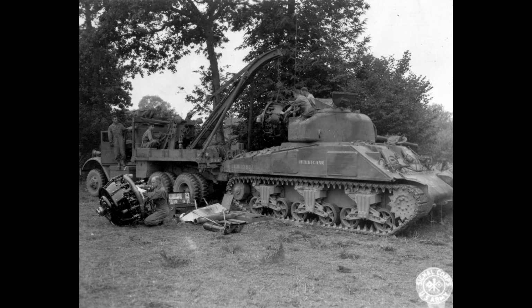The technical challenges were genuine. Welding armor plate wasn't like welding ship hulls or structural steel. Tank armor was hardened steel with high carbon content, specifically heat-treated for ballistic resistance. Welding introduced intense localized heat that could alter the metallurgical properties of the armor, potentially creating brittle zones that would shatter under impact. The team worked 18-hour days in a converted warehouse at the Detroit Arsenal.